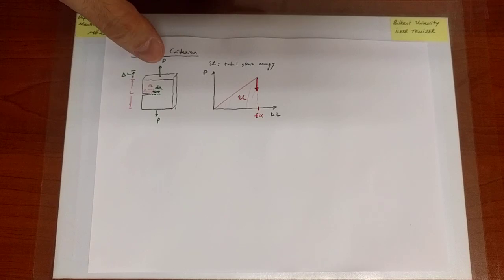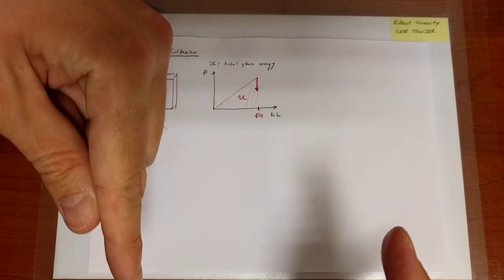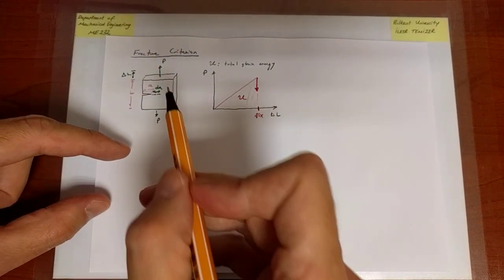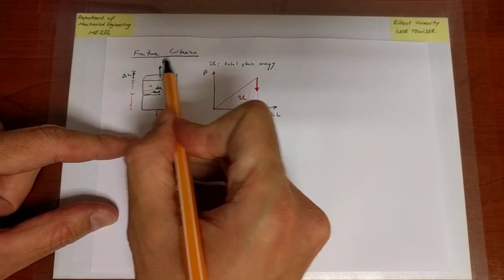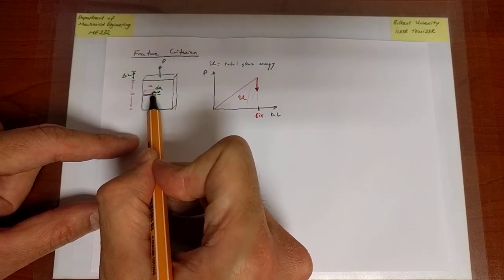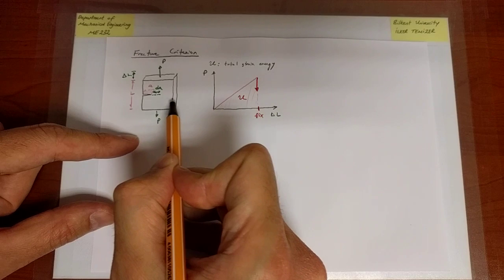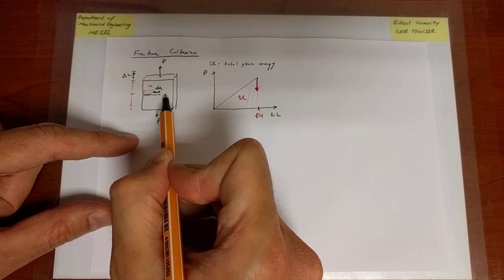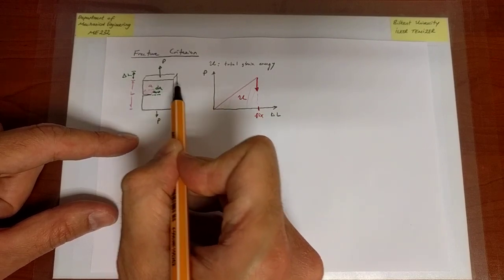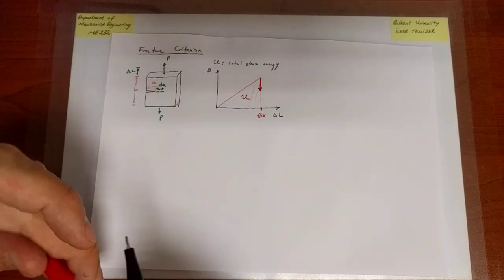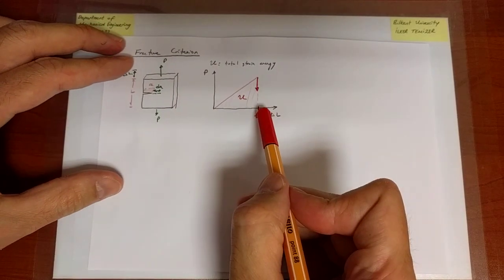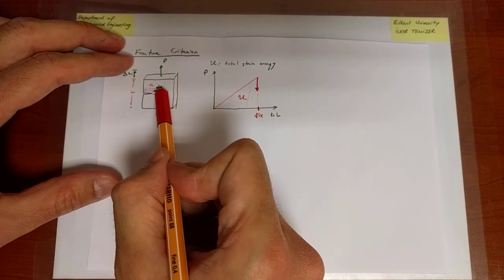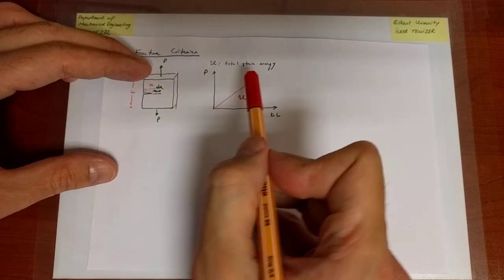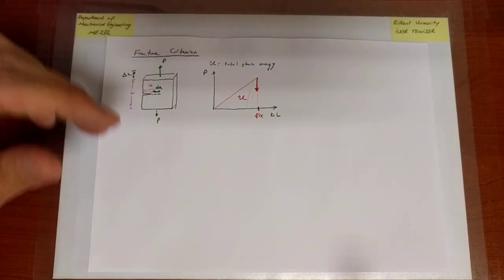Because the net force decreases in the elastic band as the tape was peeling off. So in this case, when the position of the top surface is fixed and this thing keeps propagating, the stiffness of the cross-section is being reduced because there is now less area carrying that load, and it will elongate more easily. Or conversely, if the elongation is fixed and the crack is propagating, because the stiffness is being reduced, the force that I measured is also being reduced.